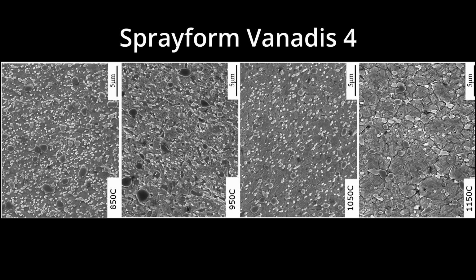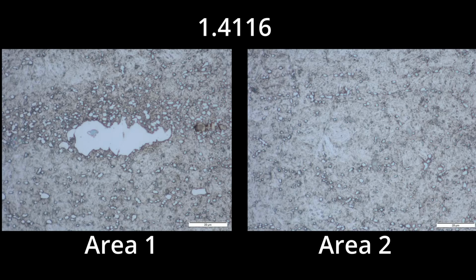So the stable, larger carbides will grow while the smaller ones will shrink or dissolve. And so you can't just hold the steel at high temperature and get rid of the carbides. They don't go away. I have seen some cases where people will advertise that they're doing a special thermal processing or a forging treatment to a stainless steel and eliminating the large carbides, but they are not. Those carbides don't go away. And what they're usually doing is cherry picking.